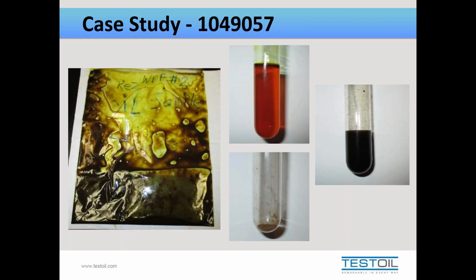So from this, we were able to determine that the source of the issue was due to a mineral water ingression problem. And at that point, it was recommended that the customer needed to find out how this mineral water had ingressed into the system. Keep in mind it is a geothermal plant, so that was part of what they used to run. But they need to figure out which part of the system had failed to allow this to enter and how to remedy that. But at least we were able to pinpoint for them what had caused this chain reaction of events: water had gotten into the system and then caused the lubricant to degrade, which created deposits in the system that prevented proper operation of the turbine.